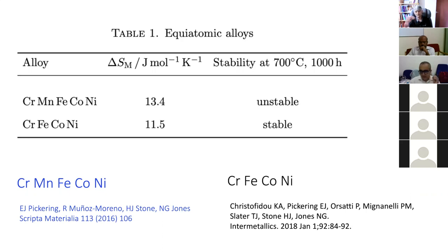And of course, if we do atom by atom analysis, then when a chromium atom reaches your time of flight mass spectrometer, you'll detect 100% chromium. And when a manganese atom reaches, it's 100% manganese. So it's not possible to decide whether the alloy is homogeneous or not just by looking at the concentrations reaching your time of flight mass spectrometer.